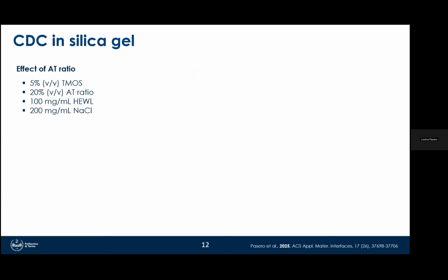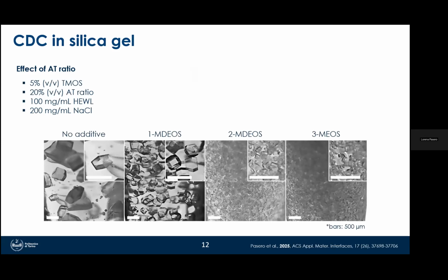And also we employed, in this case, a constant additive to TMOS ratio, which was around 20%. And we selected a high protein concentration to induce nucleation of 100 milligrams per milliliter, and the concentration of salt, which was 200 milligrams per milliliter. Here we observed how the inclusion of the additives could modify the crystallization and the nucleation pattern of lysozyme.